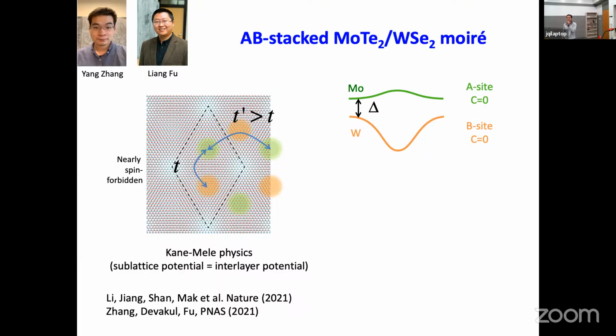Do you find AA stacking or AB stacking? Oh, it's just because each layer has a threefold rotation. It breaks the inversion symmetry, so there is a difference. You can think of each monolayer as a triangle. AA is that you put the two triangles on top of each other, but AB is that we put one triangle to be like that. So that's sort of connected to the honeycomb, you can see.